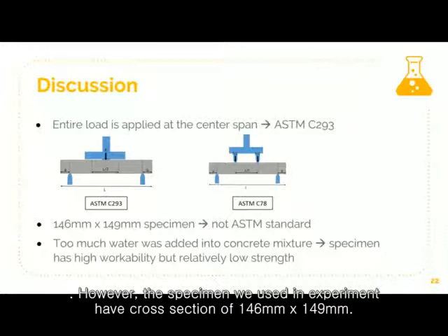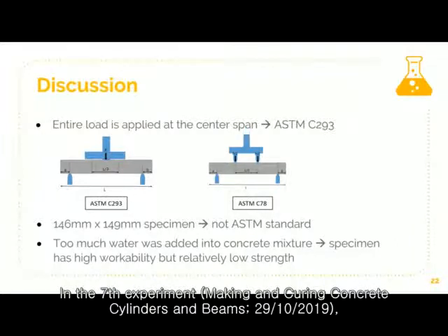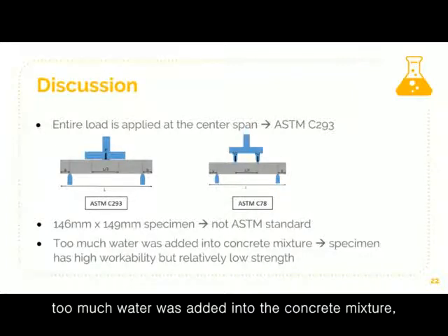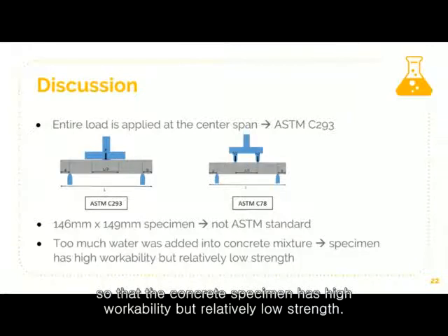However, the specimen we used in the experiment has a cross-section of 146 mm by 149 mm. In the 7th experiment, which was on 29th of October 2019, our team added too much water into the concrete mixture, so that the concrete specimen has high workability but relatively low strength.